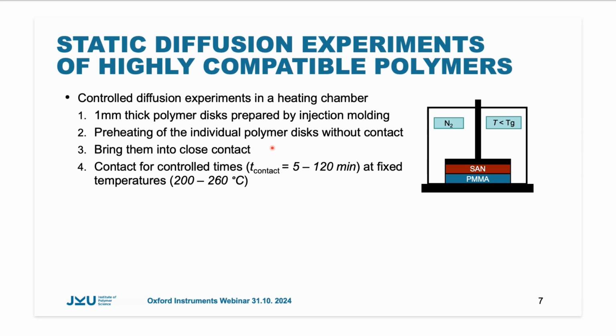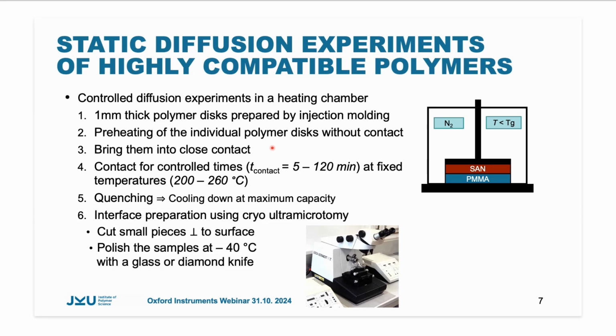Therefore, we use this. When we reached the desired time, we quench the sample down, meaning cool them down with maximum capacity. And then we prepare smooth samples using a cryo ultramicrotome, where we polish cut samples at minus 40 degrees C with a glass or diamond knife, so that we get these nice smooth surfaces, which we can then use for further investigation.